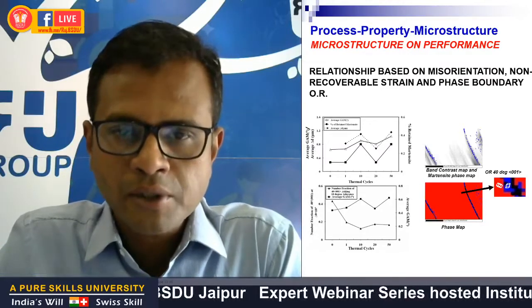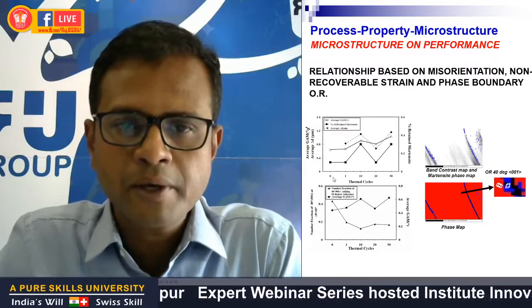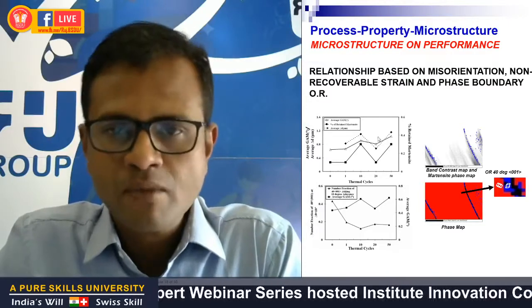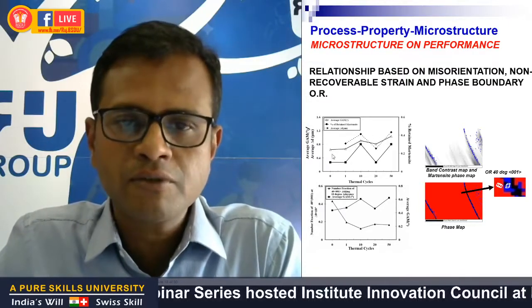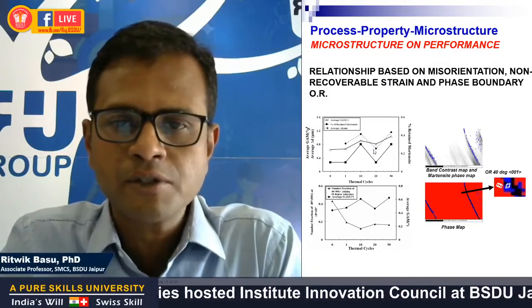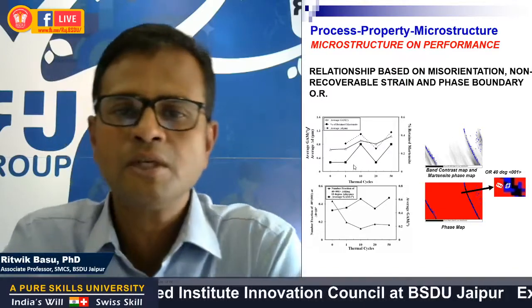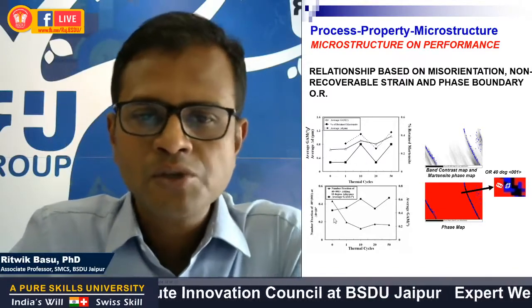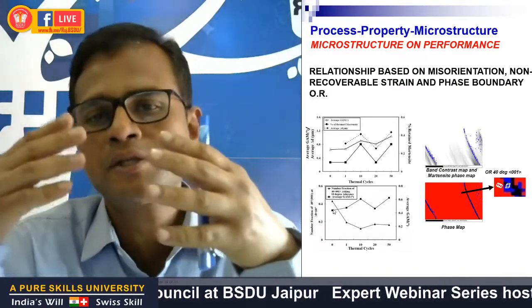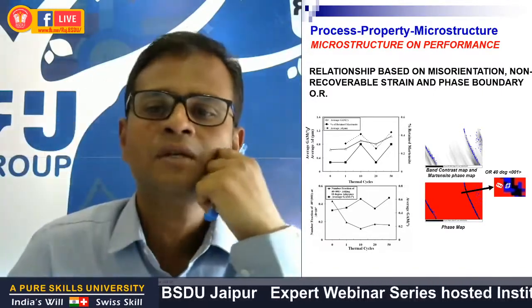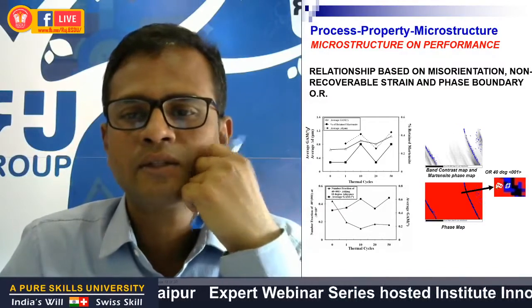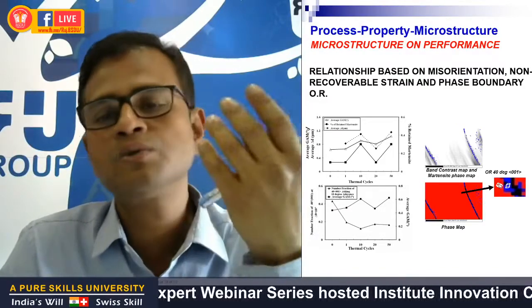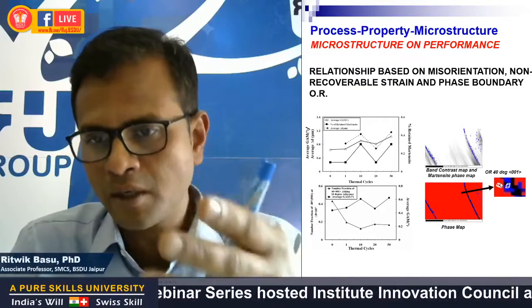So this is brought out in this plot where we had superimposed the delta D with the fraction of the retained martensite and the average misorientation estimated from the EBSD microstructure. So we found that an ideal orientation relationship exists between the austenite and the retained martensite, and that comes out to be 40 degrees <001> in our case.